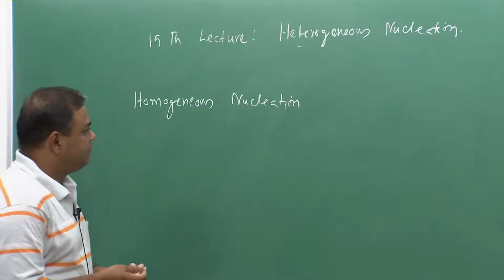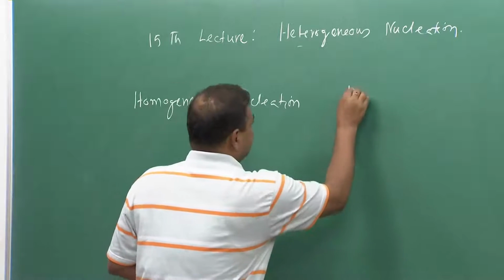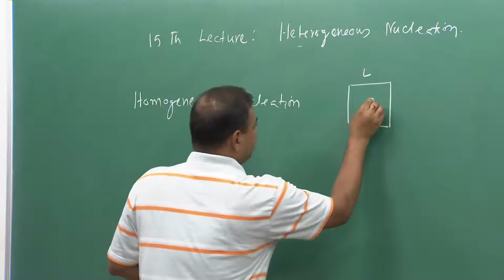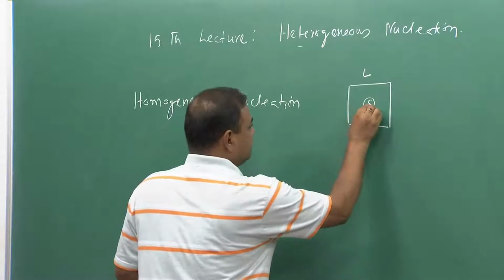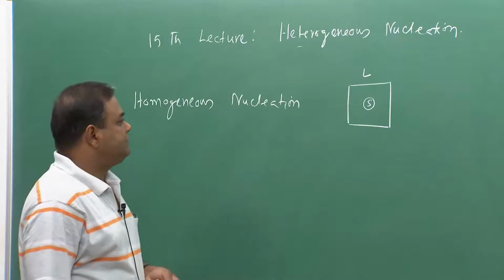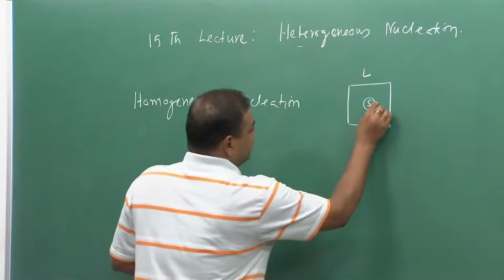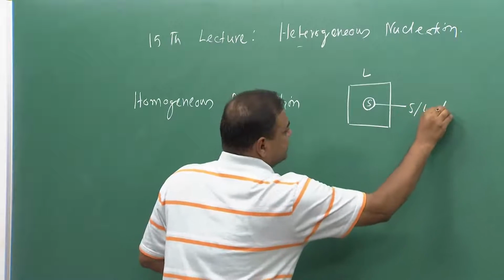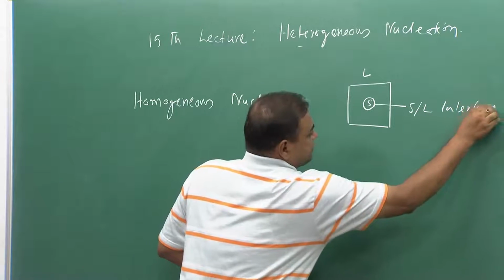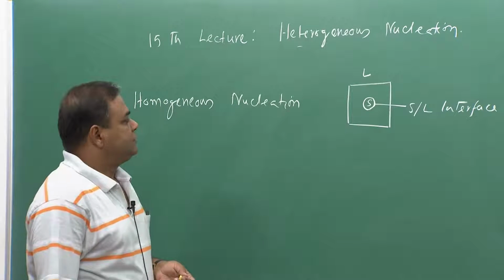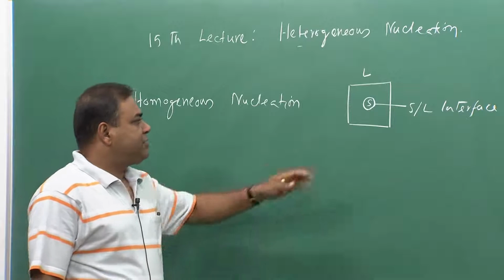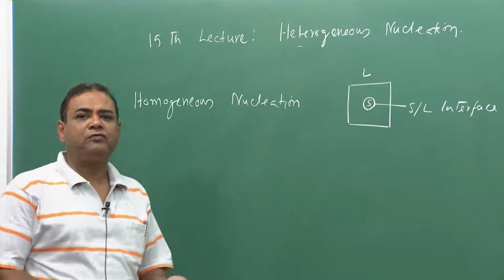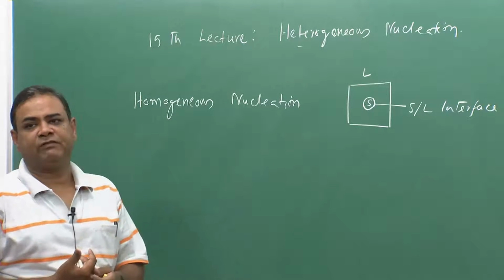So, that makes it clear that whatever discussion we had, that means in case of liquid volume, if we have a formation of a solid, at that time this solid liquid interface is the only interface. This is the only interface which is solid liquid interface. And the total energy requirement for this interface creation is coming from the volume free energy change, which is the thermal factor.